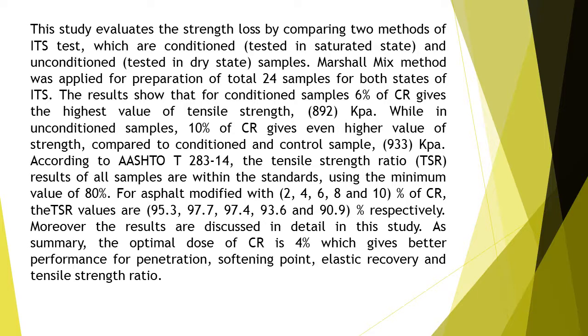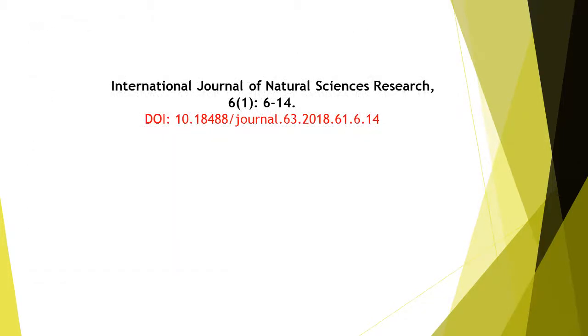As a summary, the optimal dose of CR is 4%, which gives better performance for penetration, softening point, elastic recovery and tensile strength ratio. Thanks for watching this video of International Journal of Natural Sciences Research, Volume 6, Issue Number 1.